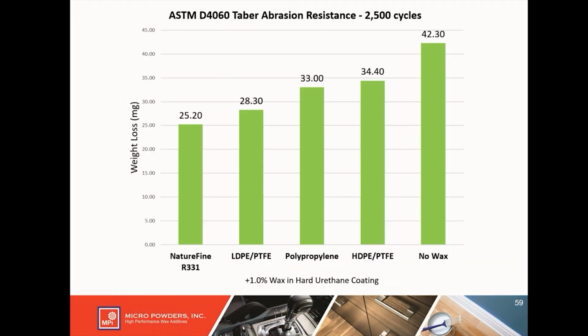So here we are again with our Taber abrasion resistance, 2,500 cycles, 1% in a hard urethane coating. We're looking at weight loss. No wax, 42 milligrams removed. The next bar, high density polyethylene PTFE, is better. Polypropylene in the very middle, also micronized polypropylene, is pretty good. That improves further on. The low density polyethylene PTFE, better still, 28 milligrams removed. But all the way on the left is NatureFine R331, micronized rice bran wax. Best of all of these additives, 25 milligrams of coating removed in a Taber test.